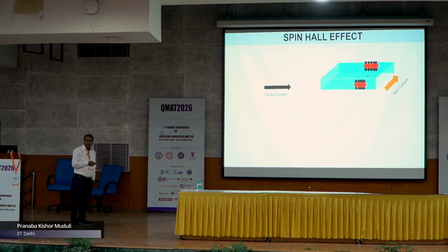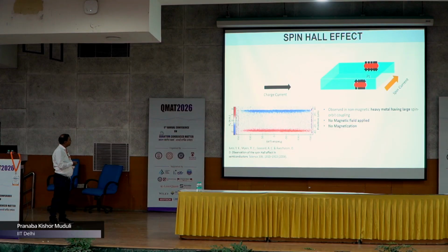like a metal, a heavy metal such as platinum, where this effect was initially predicted in theory, and later it was observed in experiment. This was the first observation using the Kerr effect on a semiconductor, and they saw this accumulation. And the way it is different from the normal Hall effect, as I pointed out, is that it doesn't require any magnetic field, no magnetization.